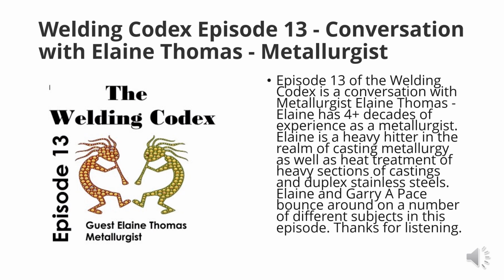The other thing is that as the part cools in the mold after being poured in whatever form it is, the metal is going to spend a lot of time between the temperatures of, say, 900 and 1700 degrees. During that time, the molybdenum in the alloy, and there is around, let's say, 2-3% molybdenum, some of them maybe even more, is going to tend to cause the ferrite, which is the matrix, to form a phase, a precipitate called sigma phase. And it basically turns the entire matrix into glass. I mean, it's very brittle. So that when the casting or the forging billet comes out of the mold, it is extremely brittle.